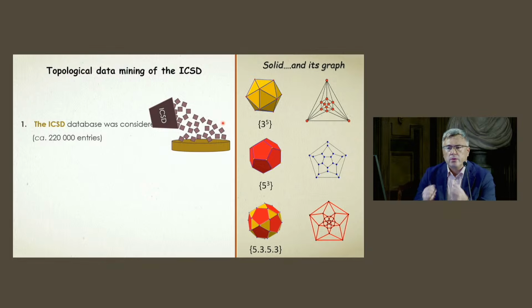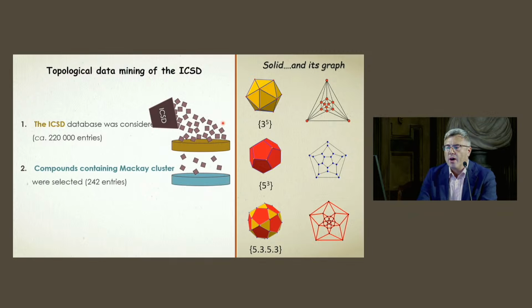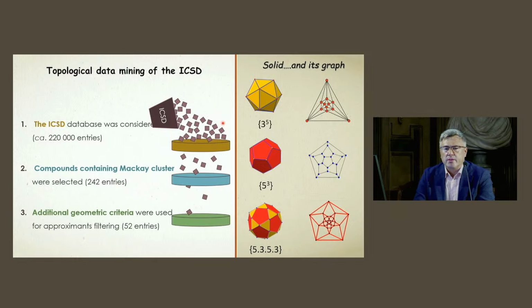We scrolled through the whole database of inorganic compounds, more than 220,000 compounds inside, and we found 242 compounds that contain Mackay clusters inside. When applying some geometrical constraints about interpenetration, etc., we filtered more, and we achieved only 52 entries that were pure Mackay approximants containing Mackay clusters.